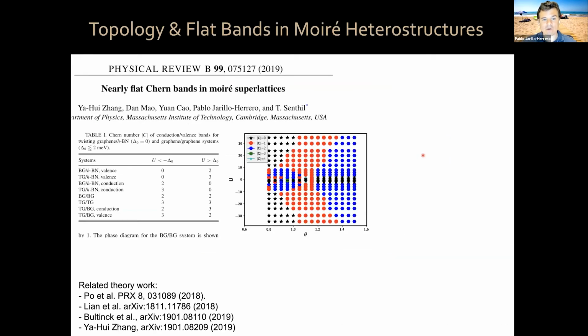Now, already in 2019, together with my theory collaborators at MIT, we discussed the existence of these nearly flat Chern bands in Moire superlattices. These were various types of Moire superlattices, where the key aspect was the breaking of the C2 symmetry. So these were superlattices which were aligned to hexagonal boron nitride. And there was plenty of other work, a little bit earlier, related to the fragile topology of magic angle twisted bilayer graphene, and also this type of structures.